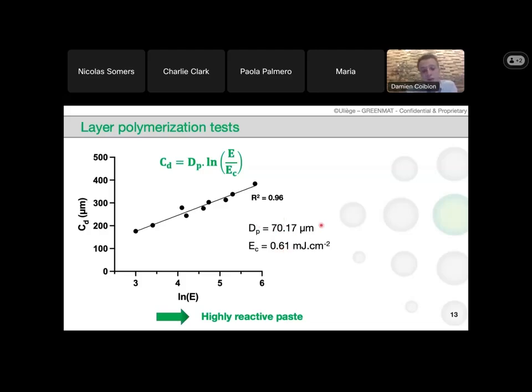About the penetration depth, we have quite the same value compared to the literature, which means that the particles are not deflecting the laser, and we have a good penetration. But the critical energy density is quite low compared to the literature, which means that our particles are not absorbing the laser, and the laser can directly polymerize our resin. So thanks to this graph, we can also control the energy required for the desired curing depth that is required for the printing.